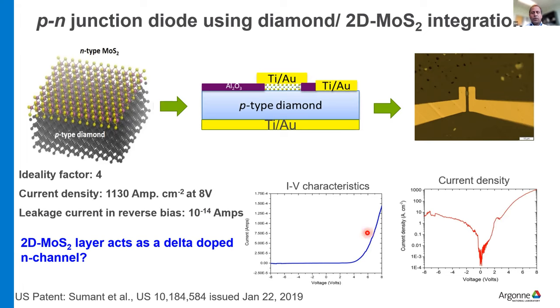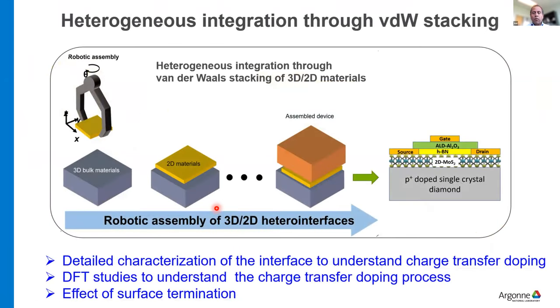And we see very nice p-n junction and diode characteristics here, with a very high current density. And the question now is whether it is really forming a junction. We are already working with theory people to think about this kind of stacking process, and MoS2 is just one material. We can think about other 2D materials stacked on top of diamond, and then do detailed characterization of the interface to understand this charge transfer doping process. And of course we can also look at how the surface termination might affect this charge transfer doping, and whether it is possible to remove this limitation of diamond on N-type doping with this kind of virtual N-type doping.